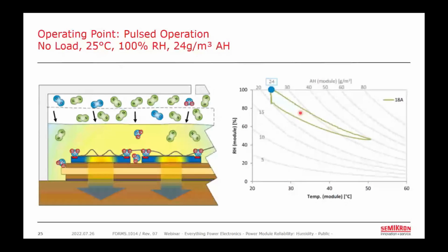The absolute humidity that we've returned to is now 24 grams per cubic meter, which is higher than that starting 20 grams per cubic meter that we registered earlier, which means that our relative humidity is also higher than before. And you can see we've started here, we went down here, and when we return, our relative humidity has sort of overshot, and instead of returning at 85, it actually reaches close to 100% relative humidity. And at 100% relative humidity, we know from earlier diagrams that the dew point is the air temperature. And if there's anything just slightly cooler than the air, there's a risk of condensation.